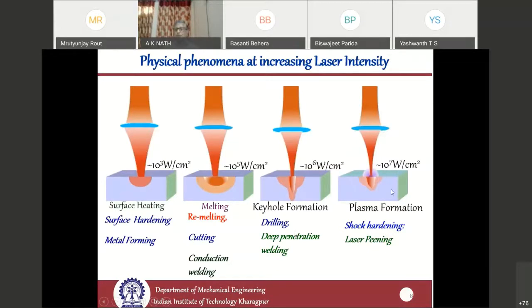When you go to even higher power densities, in the range of 10 to the power 7 watt and more, the vapor coming out can form a plasma. When the plasma absorbs the laser radiation, its temperature goes very high, so pressure also increases, generating a lot of shock wave. This shock wave can generate shock wave hardening, which is known as laser peening.